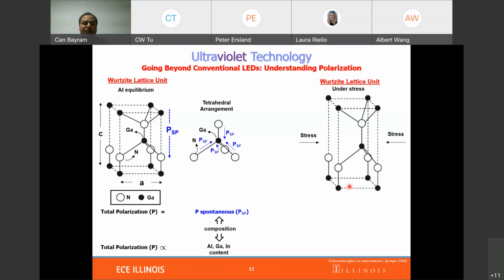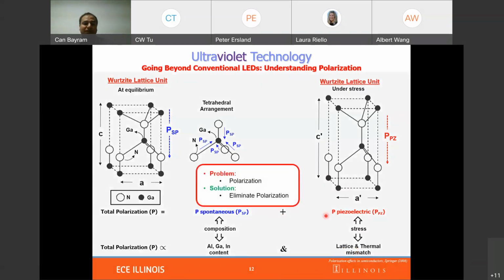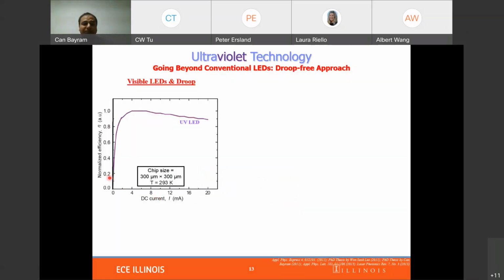So these structures are typically under stress, creating a change in the lattice constant like A prime, C prime here. Because these materials are piezoelectric, you also get a piezoelectric effect depending on the stress. That could be lattice or thermal mismatch. So overall, there is a significant effect of polarization fields, and it's very important to eliminate the polarization for next generation devices. So here is the normalized efficiency as a function of injection current, a UV LED.